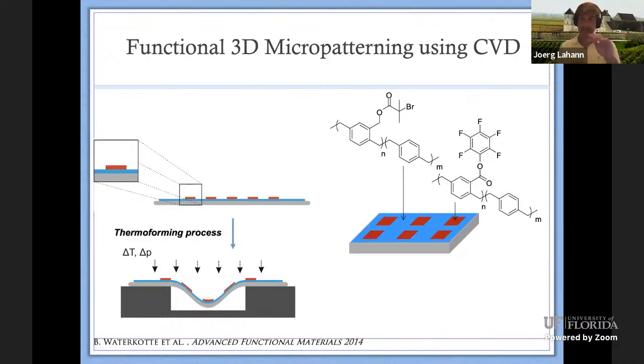So here is like a kind of an extension of that work where initially we modify a flat polymer film. So this is like a polymer substrate that has the form of a film. We pattern that, and then we basically combine this with thermal forming, so that's kind of the process that is used, for instance, to make your yogurt beakers, to then create local well structures. So you can make essentially micro well structures with intrinsic patterns already built into them. In this case, we're using two different types of CVD polymers. One is an ATRP initiator, so that is subsequently modified or initiates essentially the formation of a polyethylene glycol type material, a PEGMA, which then gives us protein resistancy.